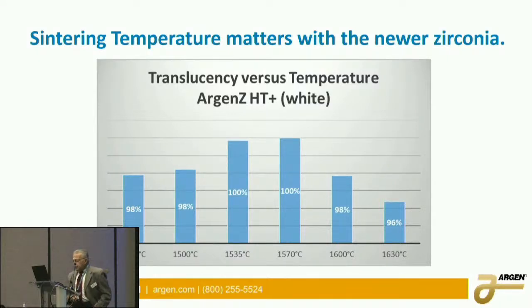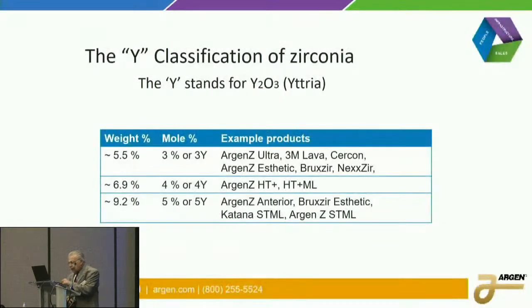Now, the sintering temperature of the 3Y, I just want to go back a minute. A lot of people saw that the 3Y material, like the Bruxer or Esthetic or the Nixer, they realized that if they fire it at a higher temperature, it gets a little more translucent. And some people were firing these up to like 1600 degrees C in order to gain that translucency. You can't do that anymore with the newer zirconias.